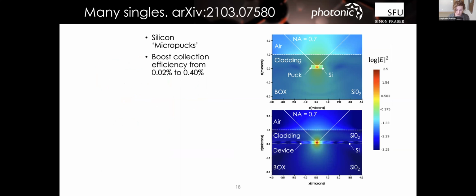So what we did is we did a lot of implantation and processing development and took a look at the characteristic spectral diffusion of these centers to make sure that they could perform the kind of optical interconnect purpose that we wanted to do. And that's going to be an ongoing thing, but there was a paper that you could go take a look at where we saw that the total characteristic spectral diffusion was about 1 gigahertz. And we've since been iterating on that internally.